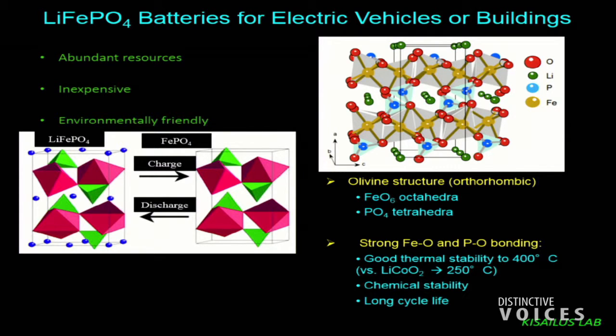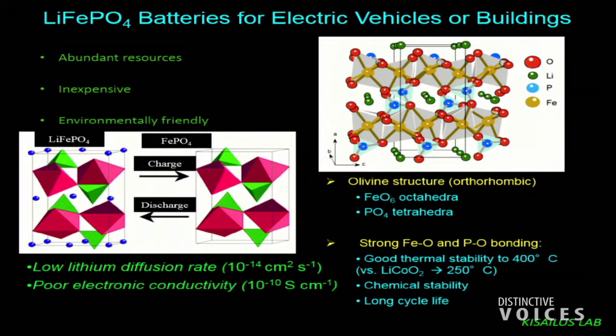It contains the iron and oxygen in an environment called an octahedra, with these phosphate tetrahedra. Because there are strong bonds between the iron and oxygen and phosphorus and oxygen, it's really thermally stable versus what's in your cell phone material. It's also chemically stable, which gives it a long life cycle. But because of those strong bonds, it has poor electronic conductivity.